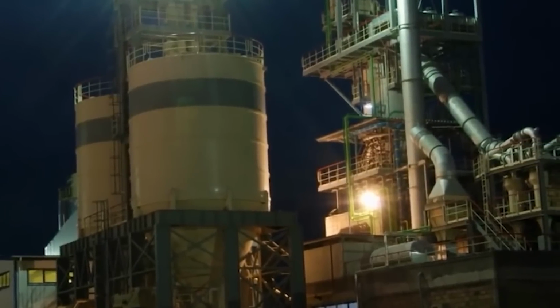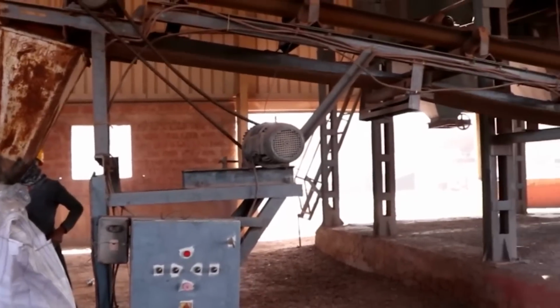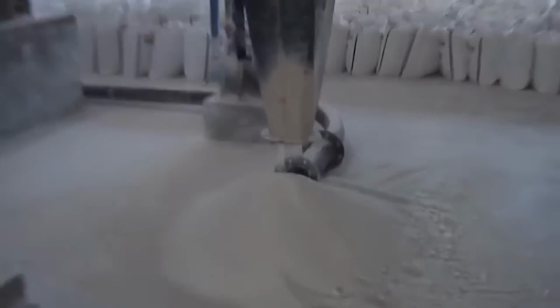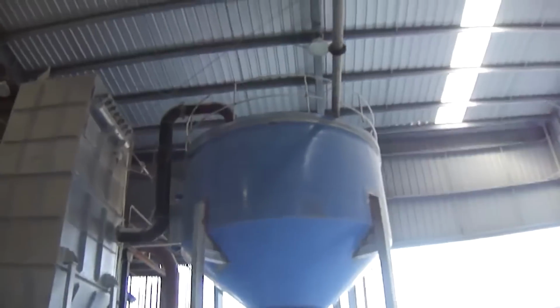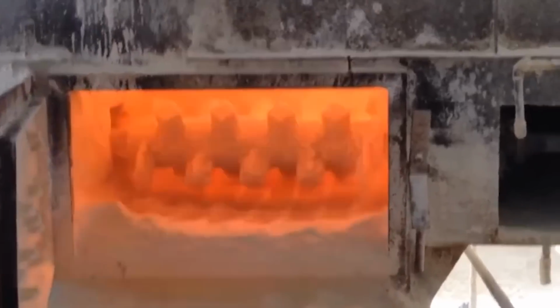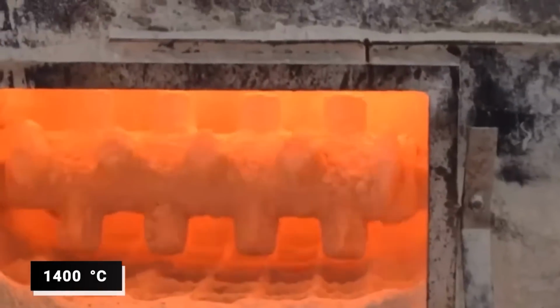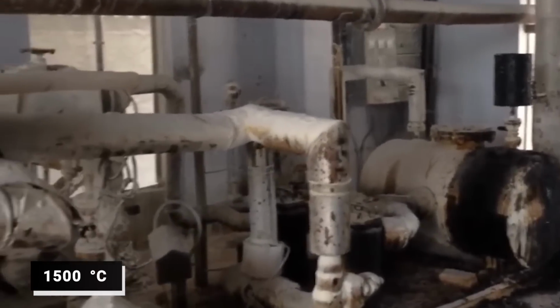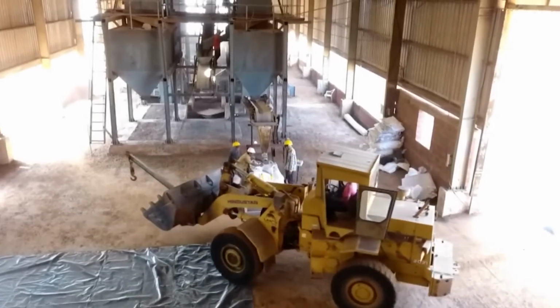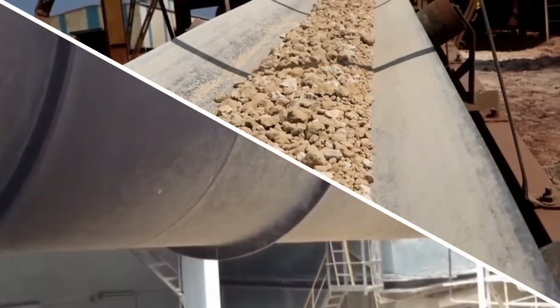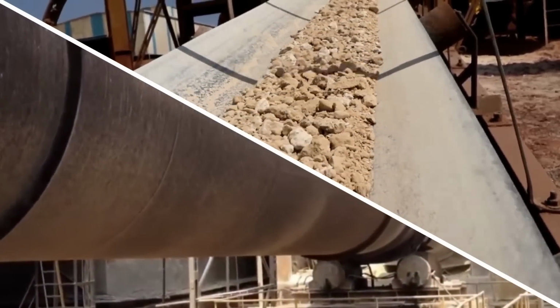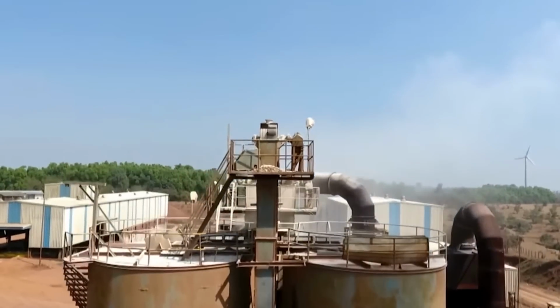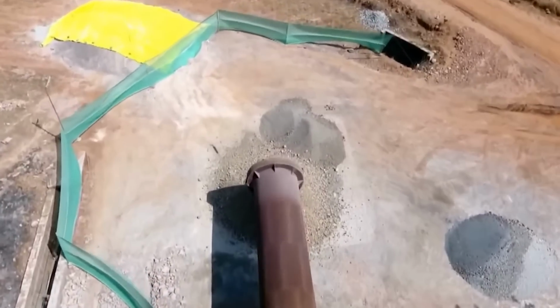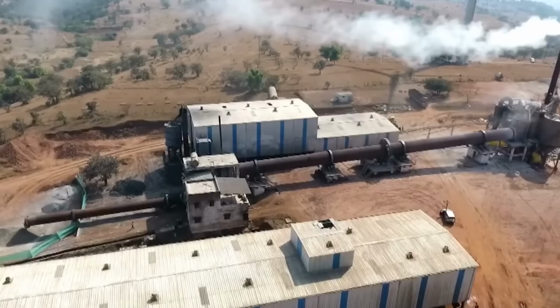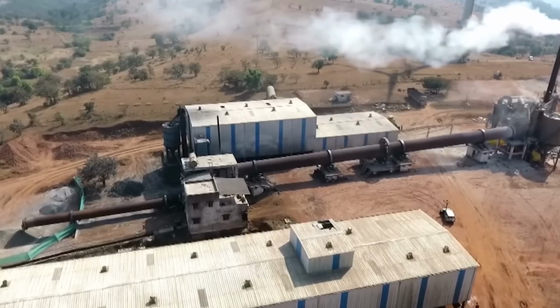on the rotary kiln. Following the calcination process, the partially calcined raw meal enters the rotary kiln, the heart of pyroprocessing. Inside the rotary kiln, which operates at temperatures ranging from 1400 degrees Celsius to 1500 degrees Celsius, further chemical reactions take place. The raw meal undergoes transformations to form key clinker minerals. These minerals include tricalcium silicate, which forms from the reaction of calcium oxide with silica and significantly contributes to the cement's strength development.